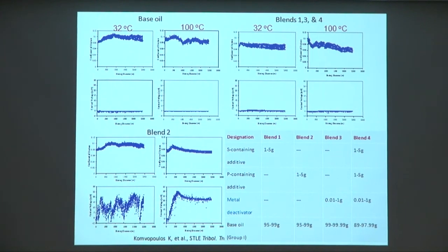we can see that begins to form the film and rapidly fluctuates. This means an unstable film at temperatures that are not enough to induce rapid reactions so that the film can rapidly form. But if we go to 100 degrees C, we can see that the film, as soon as it forms, stabilizes, and it's always forming much faster than it is worn off.